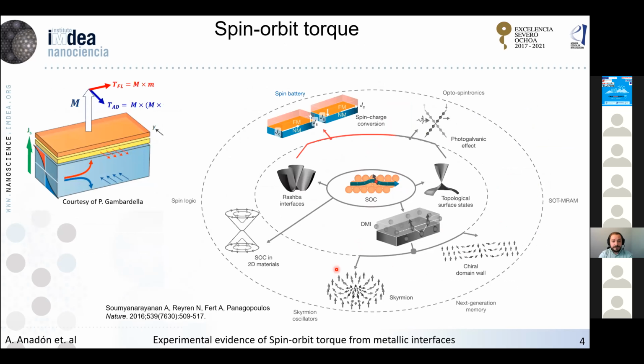The origin of all of these spin orbit torque memories comes, as we all know, from spin orbit coupling. And since we are in the spin orbit physics, you probably already know where I am going with this. From spin orbit coupling, you can have many interesting phenomena, such as the Dzyaloshinskii-Moriya interaction, which was previously discussed in some of the talks. This can give rise to chiral domain walls and chiral spin structures, such as skyrmions, which are very promising for memory applications too. But there is a handful of very interesting phenomena coming from here, like spin orbit coupling in materials, Rashba interfaces, or topological surface states. But we are going to focus here on the spin charge current interconversion.